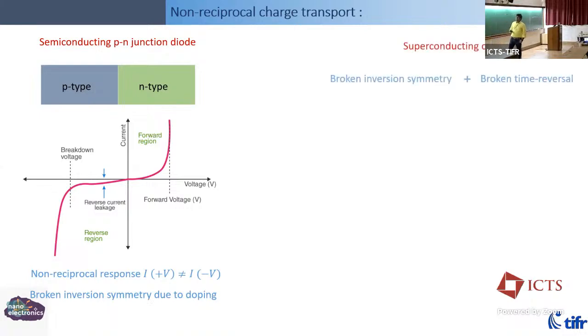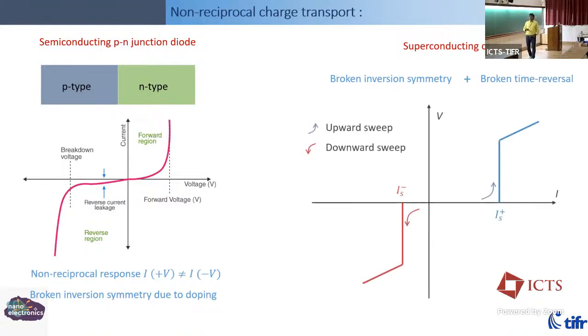So over the last several years, people have been thinking about devices which are superconducting analogs of this, which are broadly called superconducting diodes. Of that, the Josephson diode is a special kind of sub-creature, if you like. This requires broken inversion symmetry and broken time reversal symmetry. Then you can realize a device which is non-reciprocal but in the superconducting state. It will switch at one current on one bias and at a completely different value for the other direction. So it's interesting.